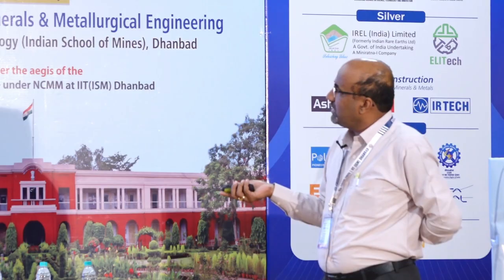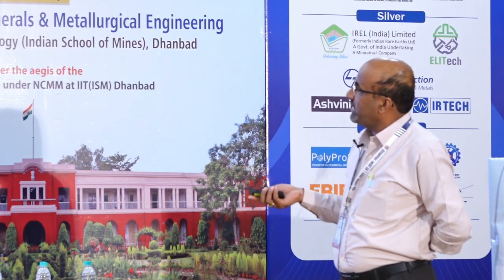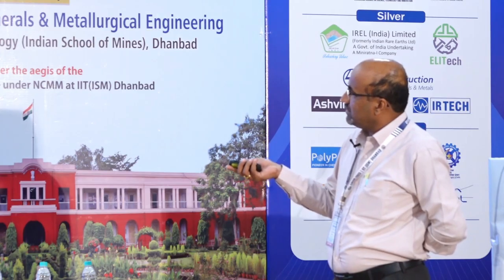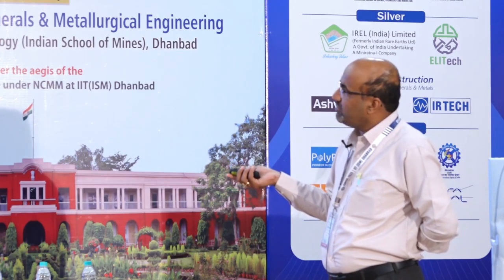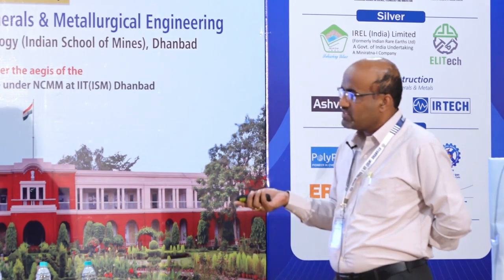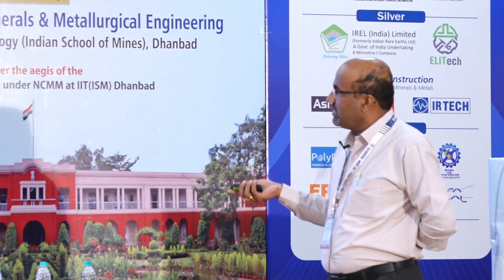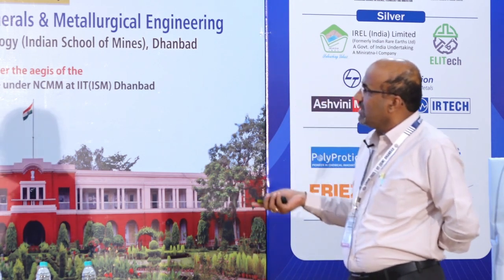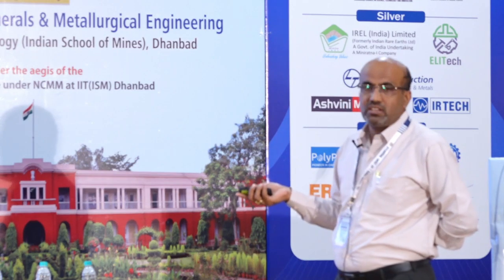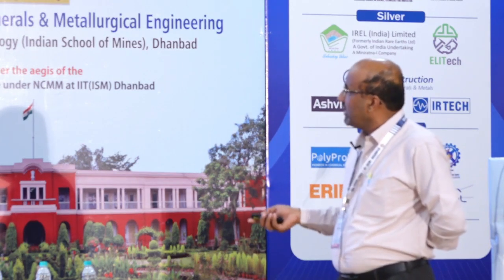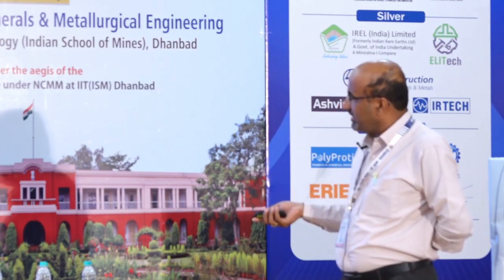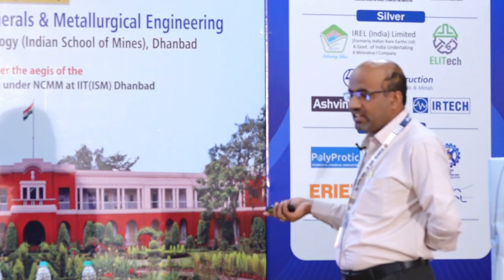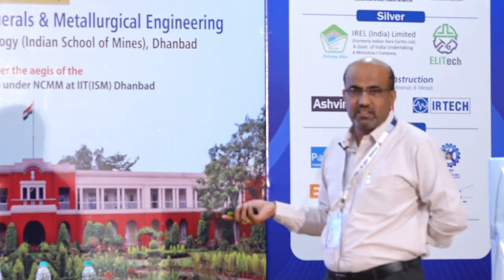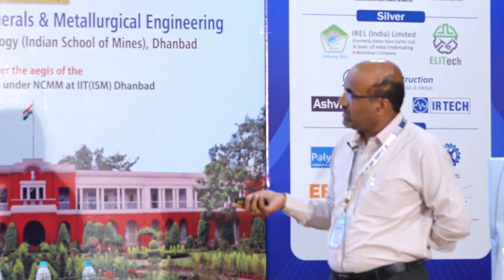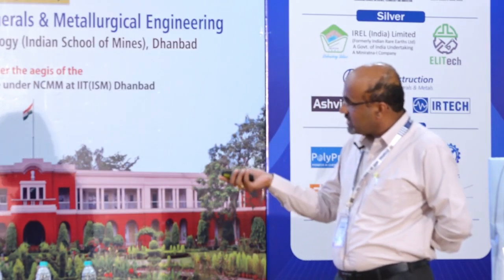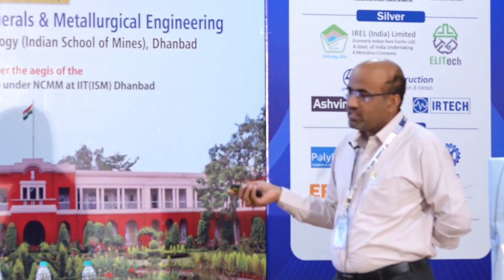Again, it is very easy to scale up to commercial scale. The properties of this solvent match very well with the current solvent extraction circuit, so there is no additional infrastructure requirement. Regeneration is easy, with stripping done with 0.5 molar HCl. Because we are not adding any thiocyanate, it becomes a trouble-free process. If you see the design, we are taking only carbon, hydrogen, nitrogen, and oxygen elements, which are perfectly incinerable. So spent solvent management is easy, and that's why I am putting this in green color, because it is becoming a green process now.